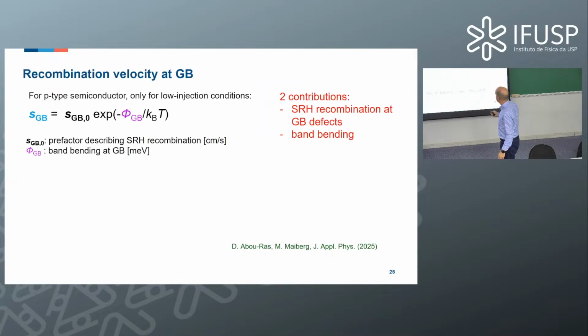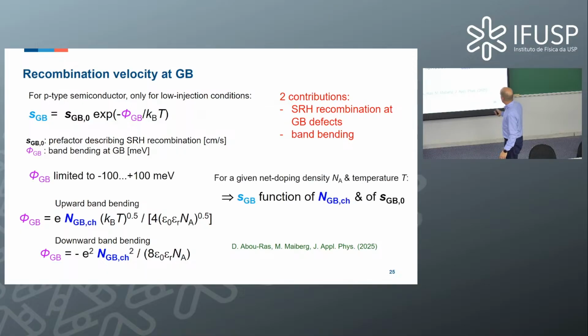Okay. And what we can now do is to say, okay, we measure recombination velocities. Let's see whether we can find appropriate values for the prefactor, and also for the excess charge density, which is one parameter describing the barrier height. If we have a certain absolute temperature, doping density and dielectric permittivity of the material, we basically only need the excess charge density that we can vary.